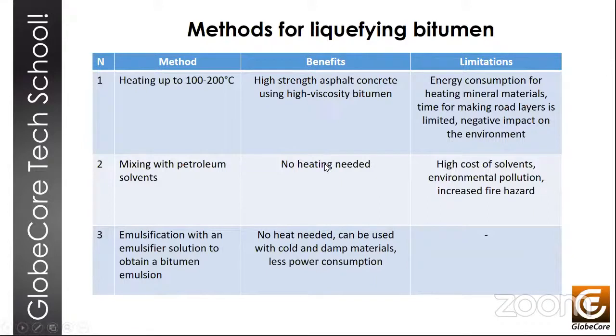This breaking starts due to the interaction of the emulsifier surfactant with the mineral material. This method, using bitumen emulsions, does not require heating, and can be used with cold and even wet mineral materials, making it possible to reduce energy consumption by as much as 40 or even 50% compared to traditional hot technologies.